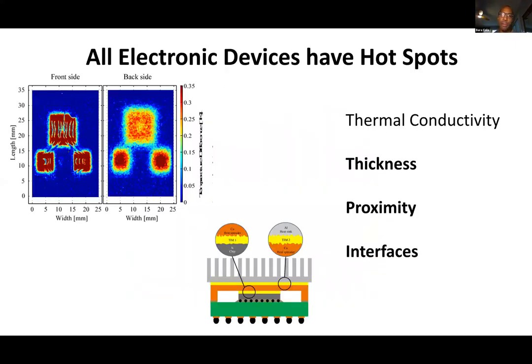So the other issue I'd like to touch on are hotspots. Clearly, this is an IGBT module at the left, and clearly hotspots are in a lot of different devices, but in these devices for DC, AC to DC, DC to DC converters for electric vehicles and clean energy, they're tremendous. But it's not just about thermal conductivity. So we spend a lot of time looking at graphene and 2D materials that can spread heat effectively, but we also need to be thinking about thickness, proximity, and interfaces. And what I mean by proximity is how close can you put the spreading to the heat source? And whenever you put it close to the heat source, you're going to have to interface it. And the interfaces can be a barrier or an opportunity in how you do the design.